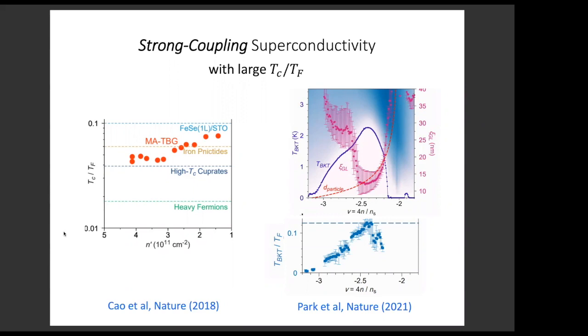And this is also the case in magic angle graphene, as well as the more recently discovered magic angle trilayer graphene. In particular, in the latter case, this very recent work from MIT, my colleague Pablo's group, shows that the Tc over TF can actually reach about 10% at optimum conditions. So this is quite remarkable. So the question then is, is there a good theory of strong coupling superconductivity from repulsive interaction, where strong coupling means a large Tc-TF ratio? Next slide.